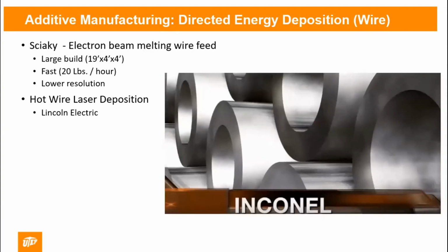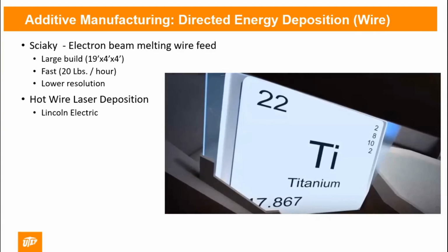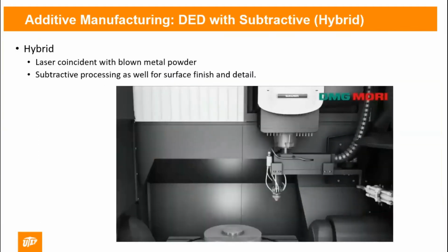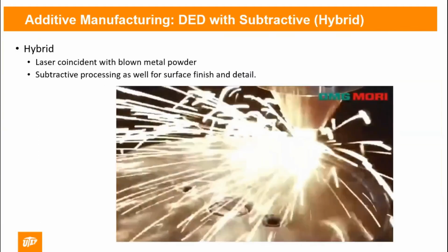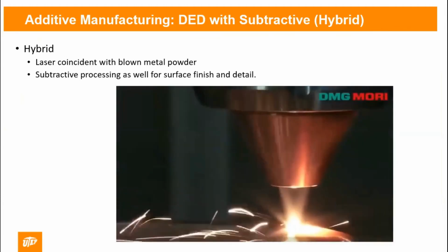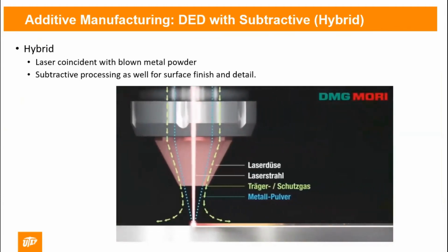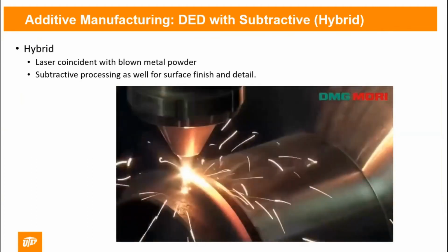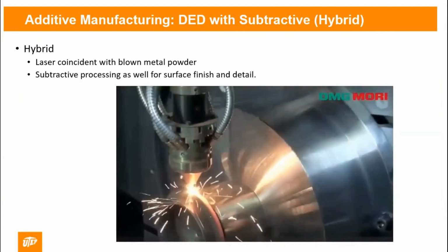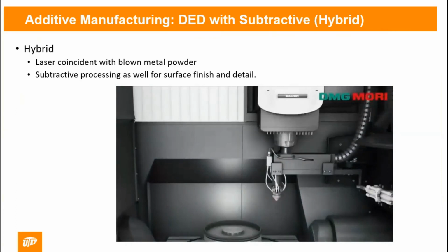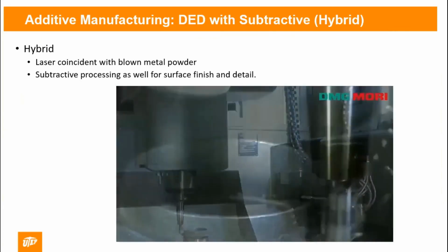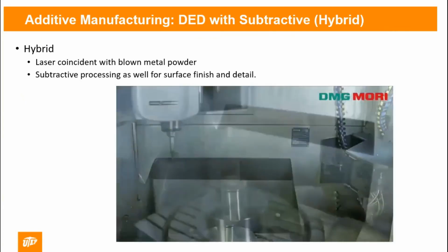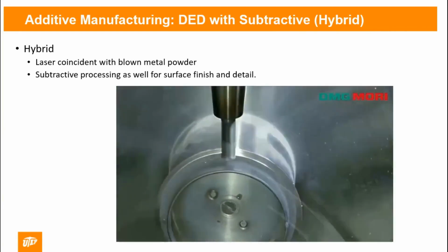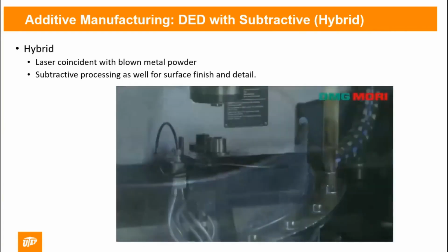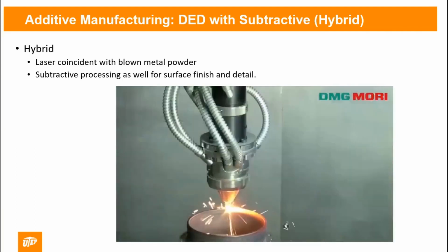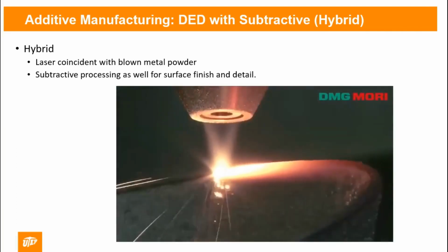And then finally, an alternative to this, or a slight modification of this, is what we call hybrid. So this is DED, a laser and a powder. You see there's both of them going coincidentally, and you can see that it's adding metal. But what DMG Mori is doing is they bring in another head, and they can actually do traditional subtractive machining to get good surface finish and intricate detail. And you can see how it's milling out holes, and it comes in and puts in another feature.